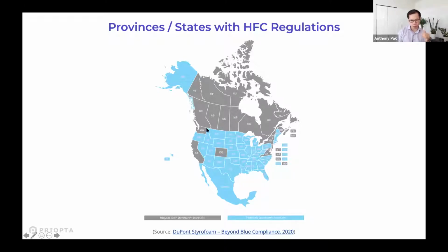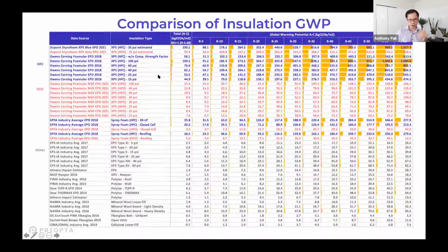So you can see all the gray ones are the ones that actually have that regulation. All the blue ones don't. So many of the states in the US don't have this. And so this is something to really keep in mind. If you're specifying XPS or spray foam, look at the blowing agent and mandate that they don't use HFC blowing agents, or that they need to use some sort of lower global warming potential blowing agent, such as HFOs, which is hydrofluoroolefins, instead of HFCs, which are hydrofluorocarbons. HFCs are the higher variety.